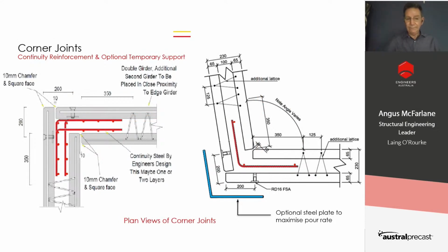Corner joints, again, virtually identical to corner joints in situ construction. Here you have 2 layers of reinforcement, which is a standard reinforcing detail. And in this one, we've only got 1 L bar in the joint. And occasionally, if you're doing very high pour rates, that's with very high walls, then you may want to put in some corner plates and structural steel to stop the joint from failing.